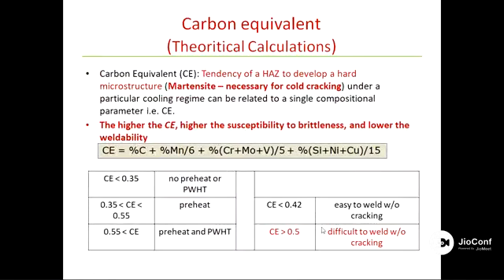Now, for carbon steel and low alloy steel, the most important thing is carbon equivalent, CE. With this formula, if you put the values of your composition into it, you can find out the value of your CE, carbon equivalent. If your carbon equivalent is less than 0.35, you need not go for preheat or post-weld treatment.